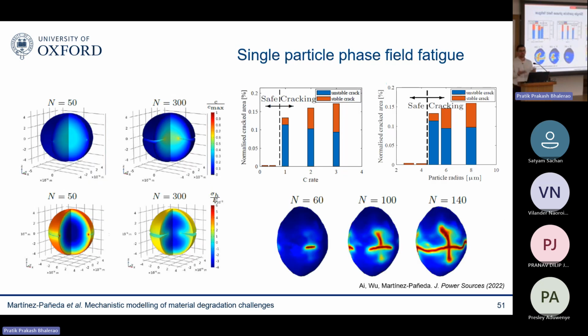And then basically you can choose the way you charge those particles. And basically, again, at the end of the day, you have a virtual platform where you can play around. You can change the shape of the particle, the defects. You can change also the way you load your particles. And therefore, you can quickly map the conditions under which things will be safe and particle cracking will not occur. And now we are also using this to test new theories.